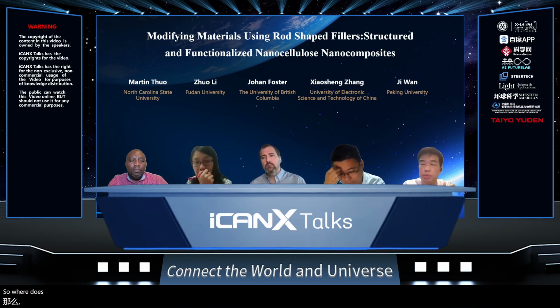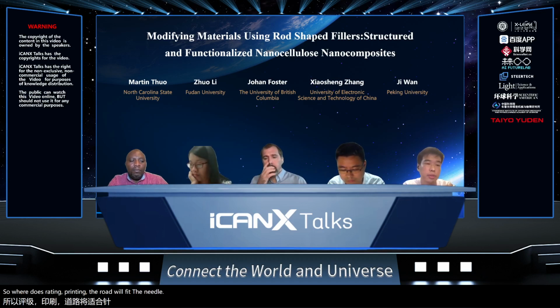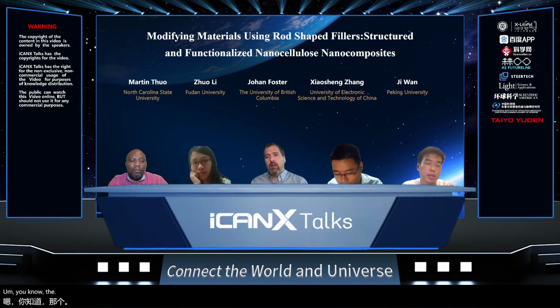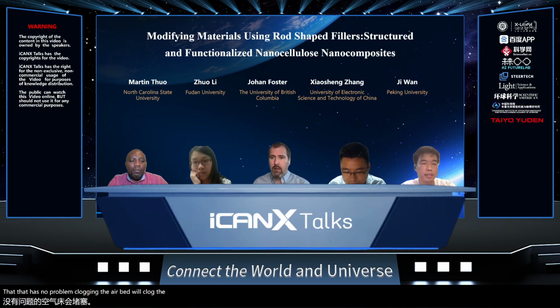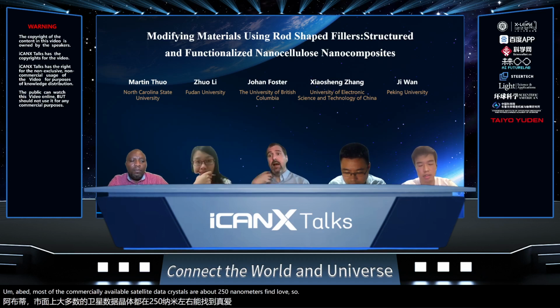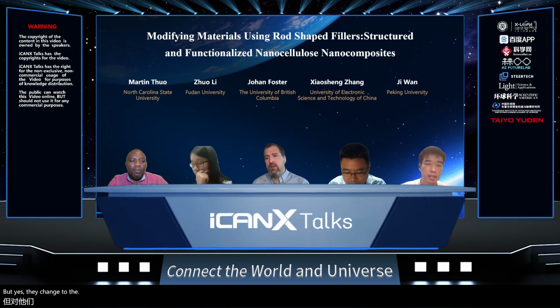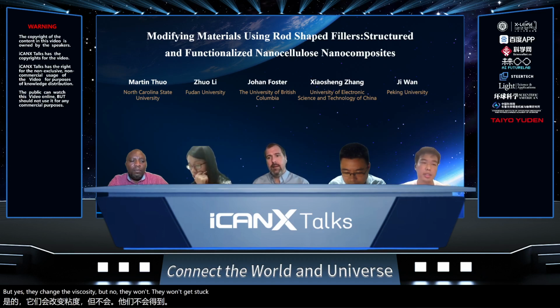So will the 3D printing, the rod will fit the needle? Yes. So for the cellulose nanocrystals, the very longest ones are, say, 4 microns. That has no problem clogging, or it won't clog the needle if done in the right way. And most of the commercially available cellulose nanocrystals are about 250 nanometers long. So yes, they change the viscosity, but no, they won't get stuck in the needle tip.